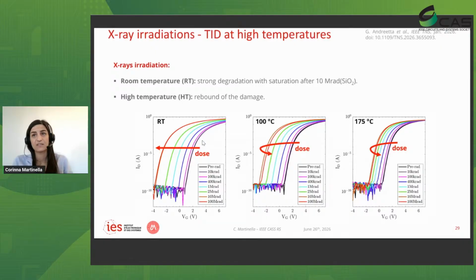However, silicon carbide also has some interesting properties that allow it to be used at high temperatures. So we did some studies where we irradiated devices and looked into TID at high temperatures. In this case, again, we were using X-rays, and we irradiated at room temperature, at 100 degrees C and 175 degrees C. Again, we saw this shift of the threshold voltage towards the left, with a saturation between 10 and 100 megarad, meaning that we are saturating the possibility to trap holes, to trap more positive charges there.